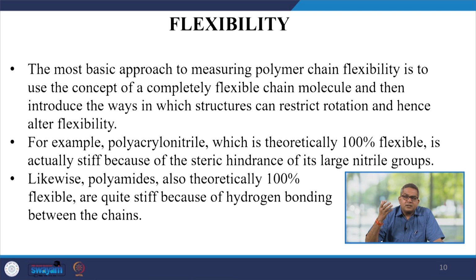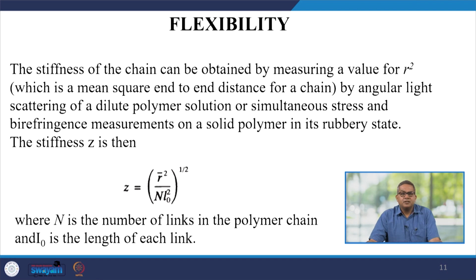Now polyamides are again theoretically 100% flexible, but they are quite stiff because of the hydrogen bonding between the chains. So, if you wish to make them 100% flexible, you need to destroy the hydrogen bonding or eliminate the steric hindrance. The stiffness of the chain can be obtained from the value of r squared, which is the mean square end-to-end distance of a chain.